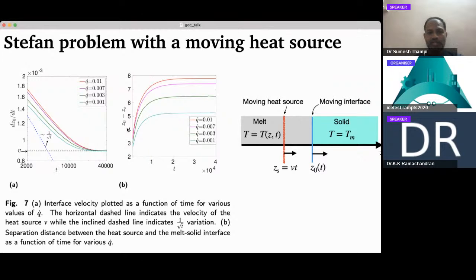And here what is plotted is z0 minus zs, basically the distance between the source and the interface. This distance is plotted as a function of time, and you can see that initially they will be very close to each other. With time it will increase and then it will reach a constant, saying that it has reached a steady state solution. You can also see that these colors are for various amounts of heat that you give, blue being the smallest and red being the largest. As you give more and more heat into the system, the distance between the source and the interface gets larger and larger. In other words, when the source is giving you a lot of heat, it will push the interface further, but the velocity with which the interface moves will still be the same as that of the heat source. So that's what the numerical solution gives.